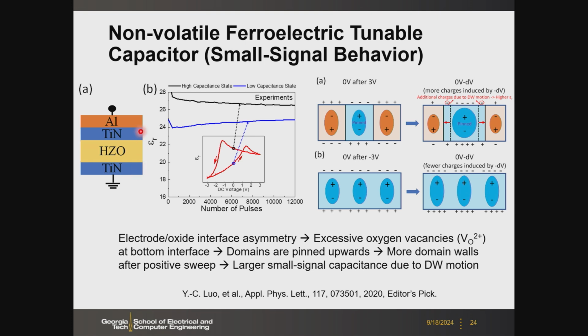So ideally, if you look at the MFM cap, then the butterfly curve, or let's say the PV loop, should be symmetric. Or let's say the CV loop should be symmetric because you have two plates, and there's no difference between the top plate and bottom plate. Then if you do the small signal CV measurement, it should be symmetric with respect to 0 voltage. But somehow in this device, we see that the butterfly curve is distorted. Right? We create an asymmetry in the CV. Therefore, at 0 voltage, we have high capacitance state and low capacitance states. We're going to use that as a mechanism to encode the data.